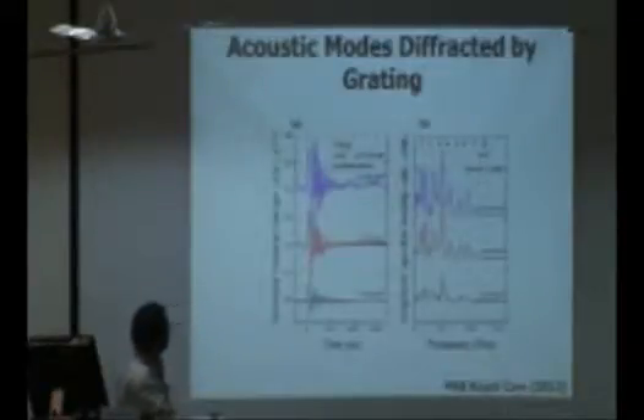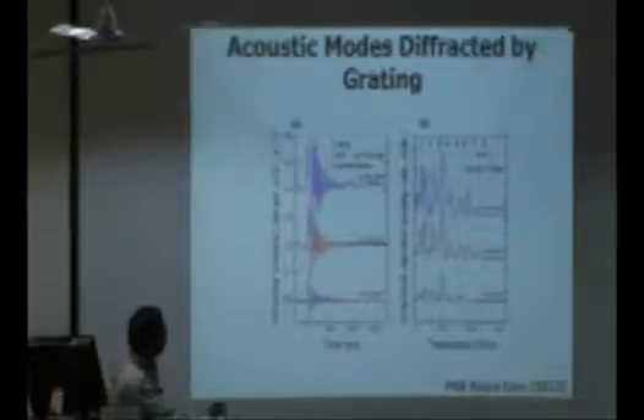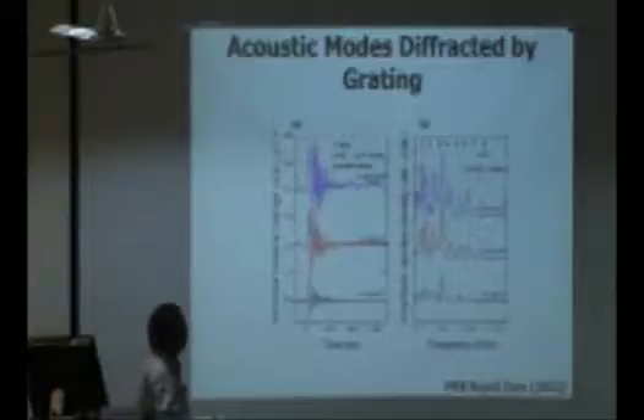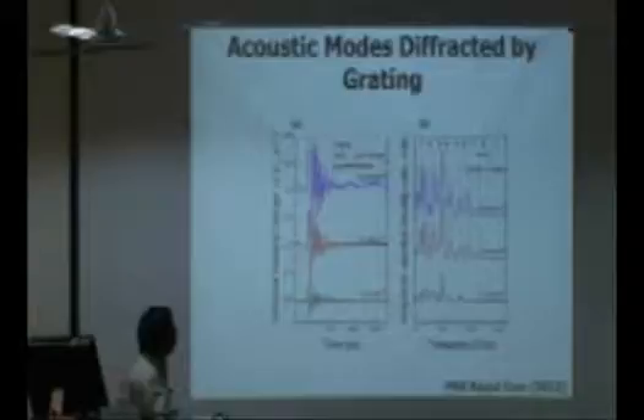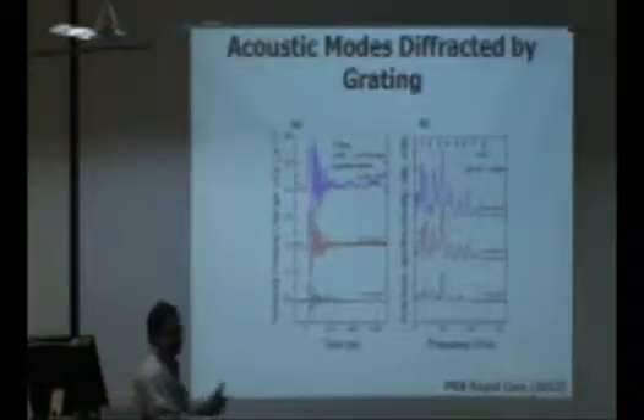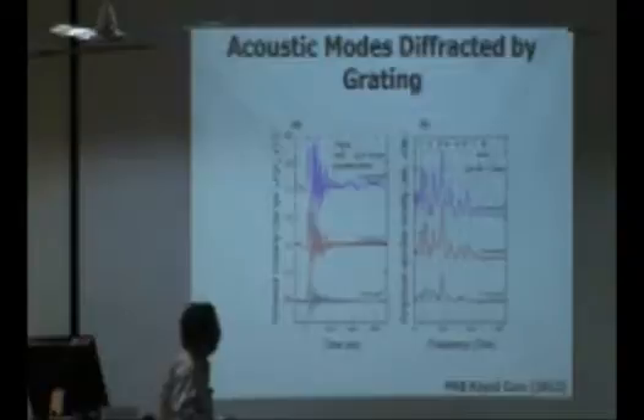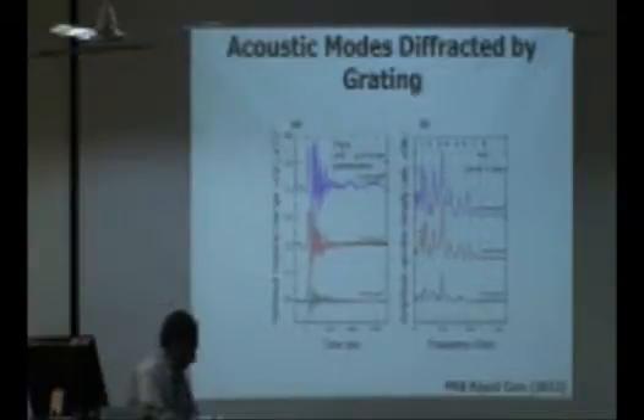Okay, so you can look at these transmissions, and we see that these lines are basically calculated acoustic phonon resonances which are expected for these structures. Okay, we show that up to 110 gigahertz frequencies, we can excite these phonon modes depending on the strength of the acoustic mode which is excited.